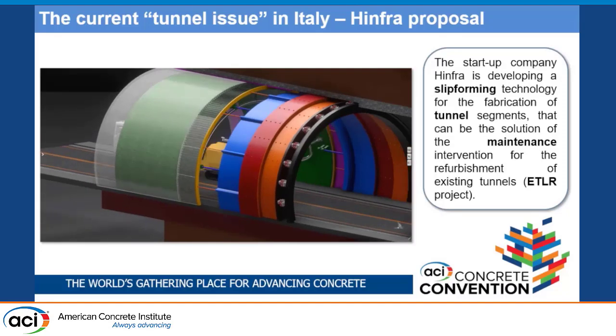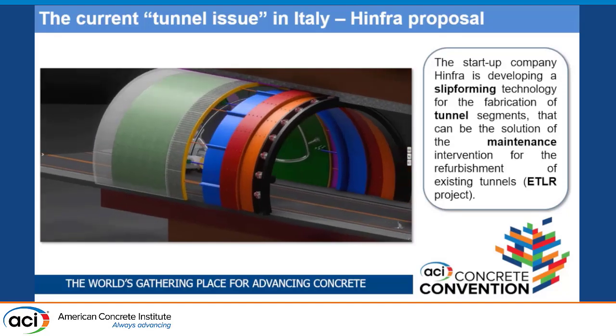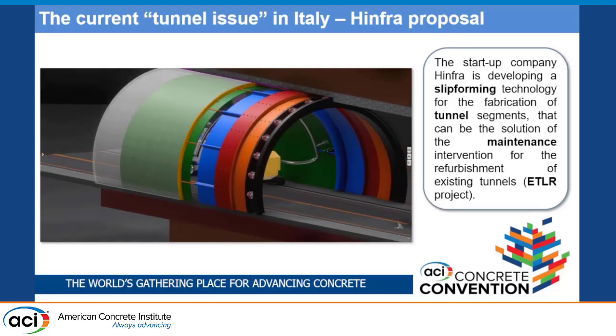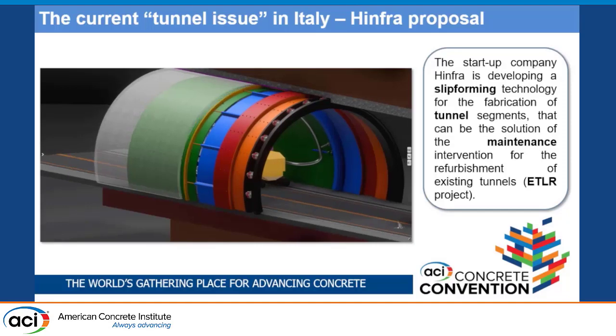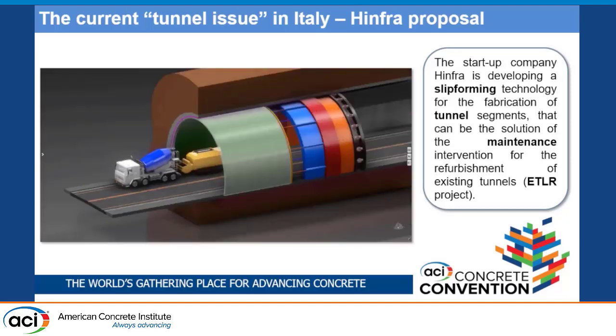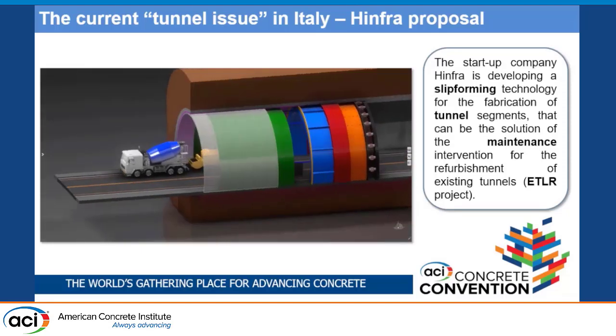Actually, this technology has been avoided and the concrete contains only steel fibers. By the way, the first step is to scrape a layer of the existing tunnels and then to fill the gap with the extrusion, the casting of new concrete.